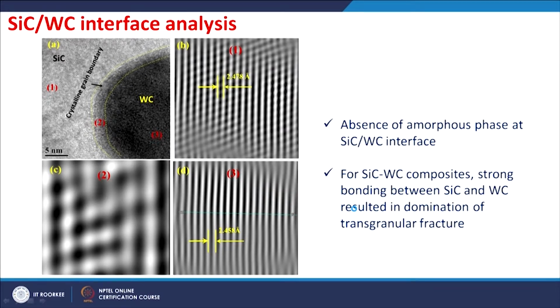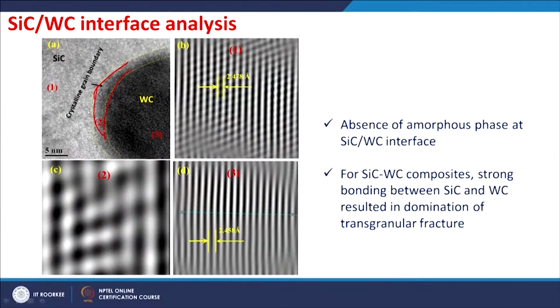The high resolution TEM analysis shows the interface does not have any amorphous region. So, the tungsten carbide as well as the silicon carbide grains are very strongly bonded. This strong bonding resulted in the domination of a transgranular fracture, which we already saw in the fracture surfaces of this composite. The intergranular fracture mode was dominant when there was no tungsten carbide particle. In the case of the composite having tungsten carbide particles, you have dominantly transgranular fracture.